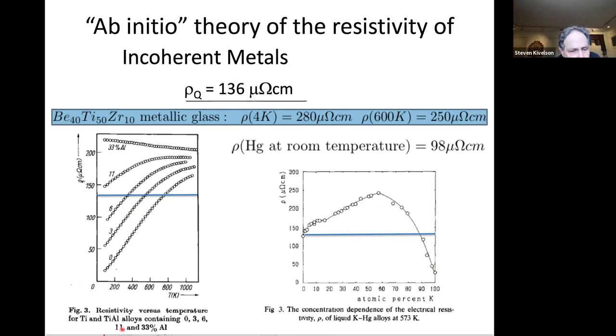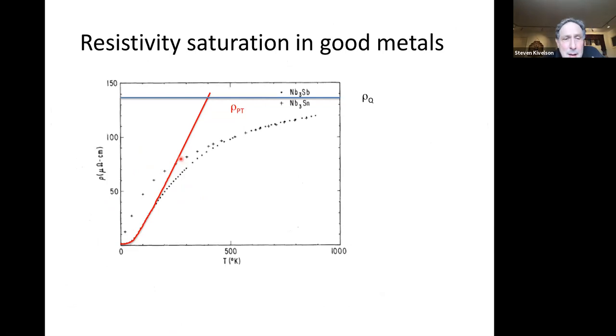Here I found some binary alloy, titanium aluminum. When it's pure titanium, then at least at low temperature, the resistivity is much less than the quantum of resistance, but it rises to values at 1,000 Kelvin that are right of this order. Once we alloy it with aluminum, it becomes more or less temperature independent and roughly equal to the quantum of resistance. This is the famous case of resistivity saturation.